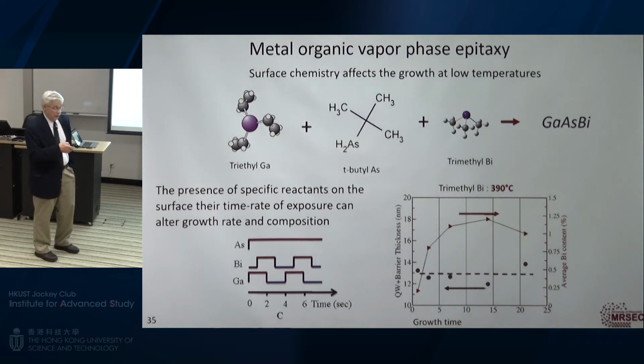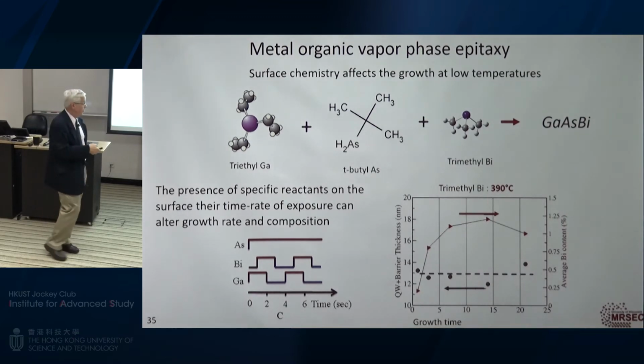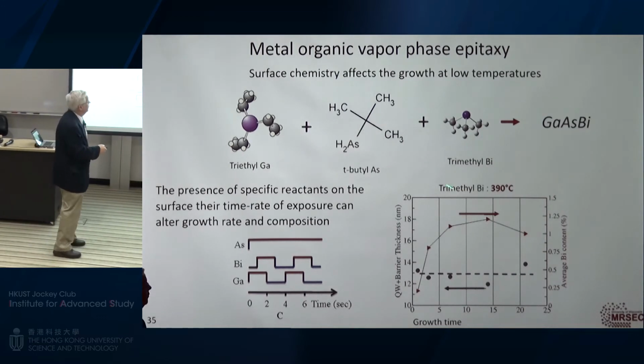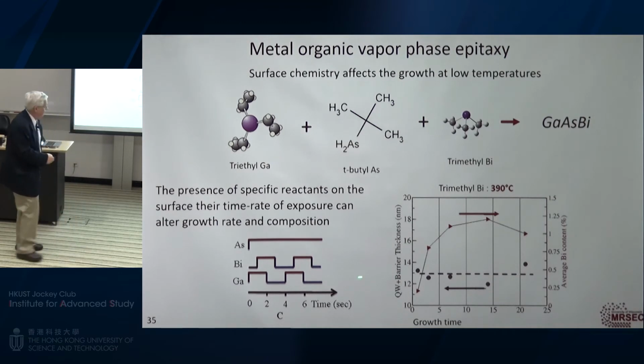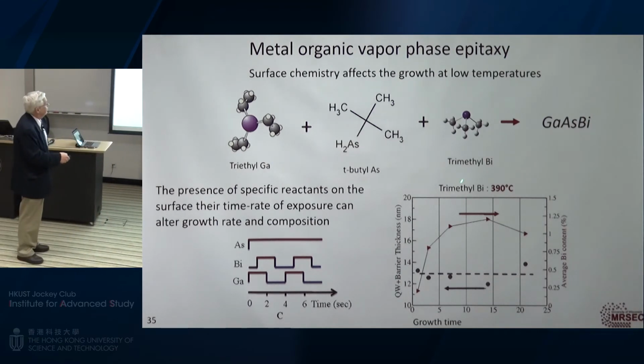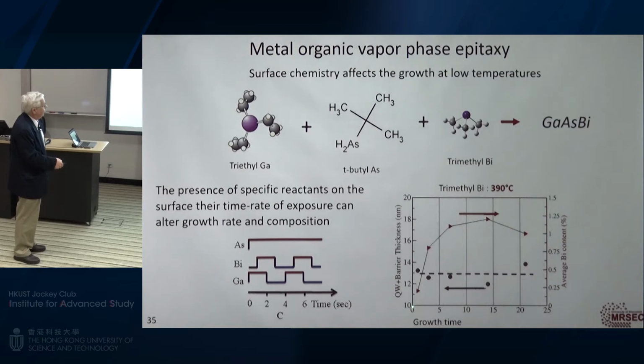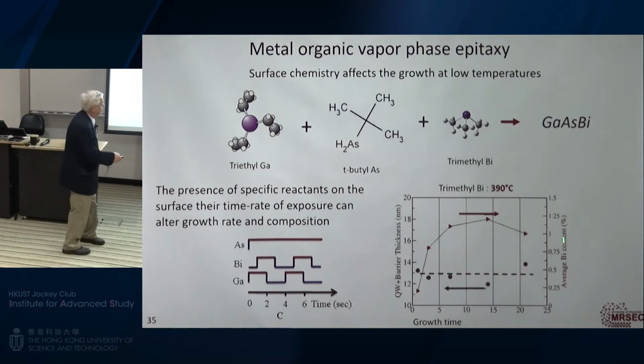And there are a variety of reasons. The bismuth has no pathway, cannot diffuse on the surface at low temperatures to find another bismuth atom to start forming that metal droplet. So it has to go into the crystal. So I basically use low temperatures to minimize surface diffusion. But there's more than that going on. What's shown here is a graph. It shows that while I'm growing, let's say I put this and this into the reactor to grow this compound, I'll get a certain amount of bismuth into it.